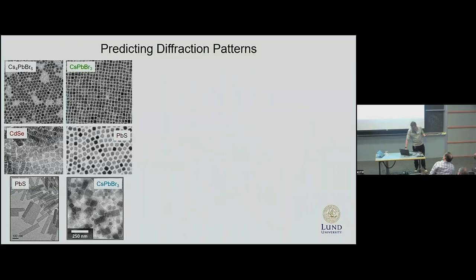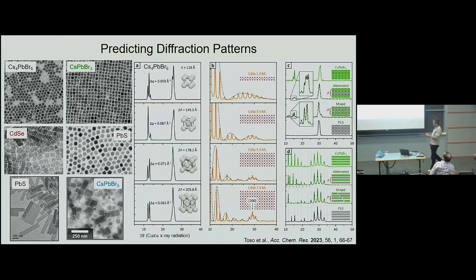By applying the routine we wrote to feed the data, we can use it to calculate diffraction patterns for various hypothetical well-ordered superlattices. If we try to assemble these probably quasi-spherical nanoparticles, depending on the geometry they assemble in, we might distinguish them, or perhaps not.